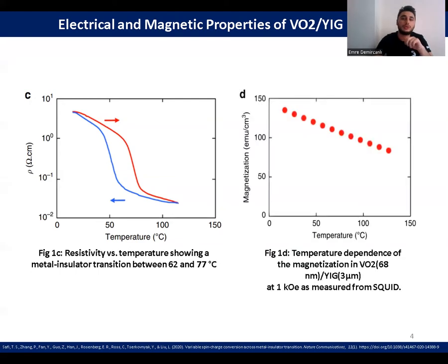Based on these measurements, the intervals with dramatic decreases are seen in the figure. In addition, hysteresis loop formation can be clearly observed in cases of increasing and decreasing temperature, as we can see in blue and red color. On the other hand, in figure 1d, we see the variation of magnetism with temperature. Magnetic measurements on YIG films were made using a SQUID magnetometer.